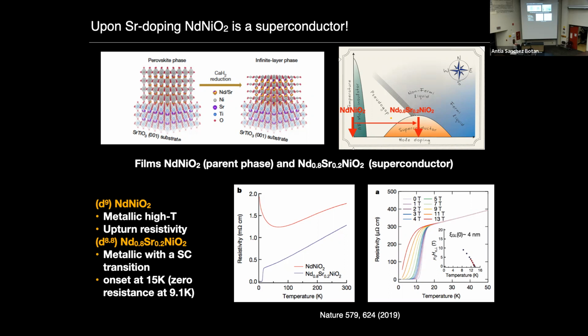So what you see down here is the resistivity versus temperature curve. For the parent phase in red, you can see it's metallic at high temperature with a low temperature upturn in the resistivity. For the doped system in blue, also metallic, but with a big surprise: it shows a superconducting transition whose onset is more or less at around 15 Kelvin. What you see on the right is just one bit of the magnetic response. This is the temperature dependence of the magnetoresistance, where you see that we have very little magnetoresistance in the normal state, and then a suppression of superconductivity upon an increase in field. There are some other parameters here that I'm going to talk about later on when I get to the 5-layer system.